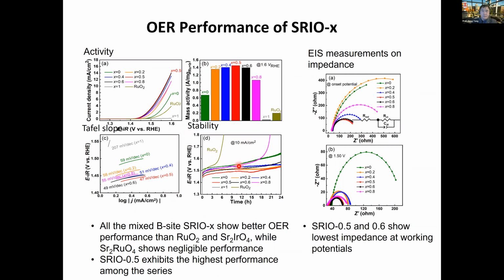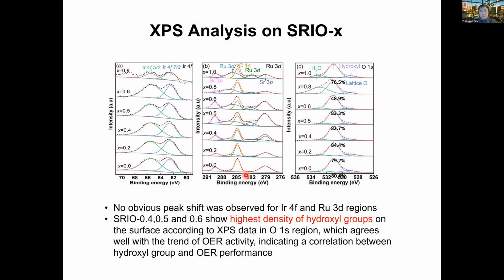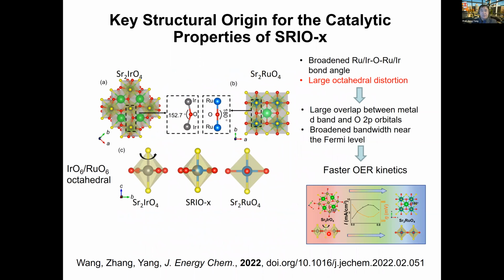Again, in this particular case, what we have observed, because of the structural flexibility and the possible, let's say, removal of the rock salt layers, is a higher density of hydroxide groups on the surfaces. And so that we think could benefit either mechanism. Okay, so in either mechanism, this high level of hydroxide groups is the intermediate state that could be beneficial to them. So that's what we think goes on in this particular case.